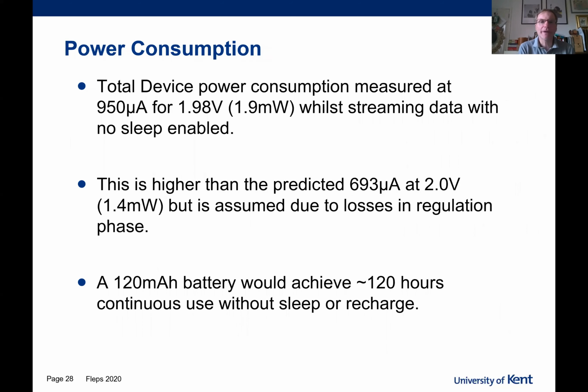Now, the power consumption measured for the system came out at a current draw of 950 microamps for just under a 2 volt supply, which is just under 2 milliwatts. This is while it's streaming the data, and there is no microcontroller sleep mode enabled, so this is not running at its optimized power efficiency. So we're running at less than 2 milliwatts. It's a little higher than we anticipated. We were expecting a draw of just under 1.5 milliwatts, and it's assumed that the extra loss has occurred basically because of the regulator used on the tag.